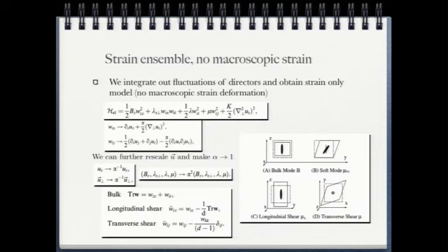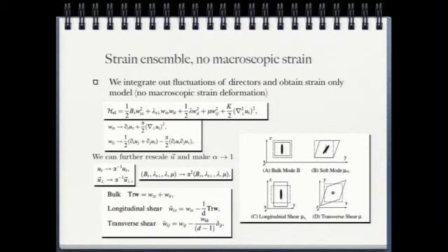After doing that, we end up with the 4 elastic moduli plus 1 Frank constant. And we found that the appropriate nonlinear strain tensor looks like this. So the only relevant nonlinearity is that of the uz field. And to simplify this expression, we further rescale the phonon fields so that this nasty factor alpha goes away. It becomes 1.